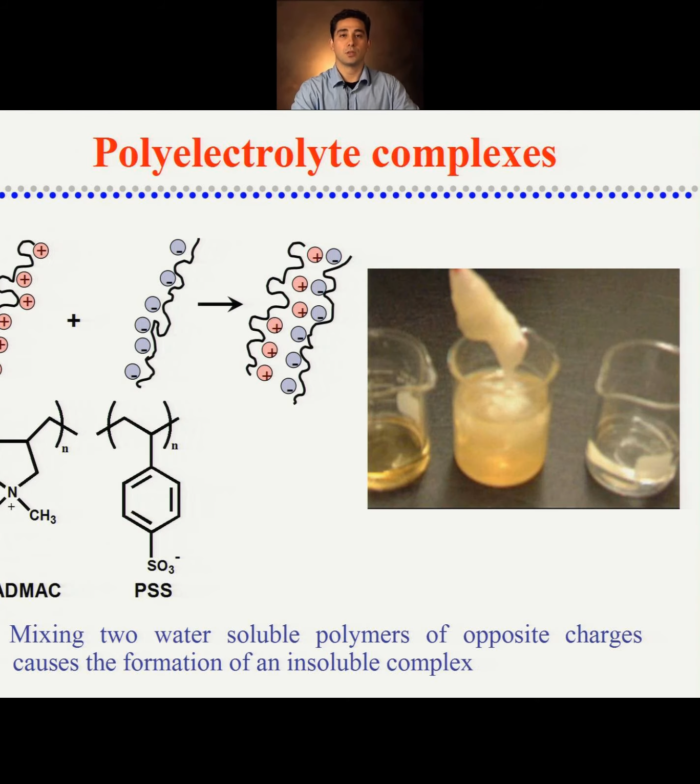Polyelectrolytes are charged polymers, and polyelectrolyte complexes have been known for a long time. The idea here is if you mix two water-soluble polymers of opposite charges, like polydiallyldimethylammonium chloride, which is a polycation, with polystyrene sulfonate, which is a polyanion, you will get an insoluble complex.